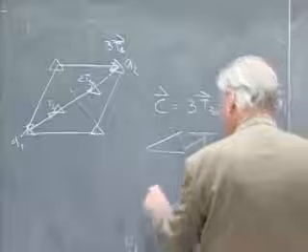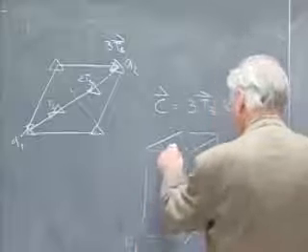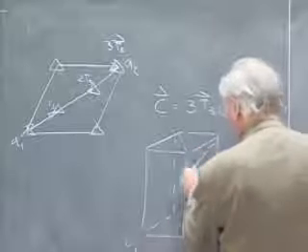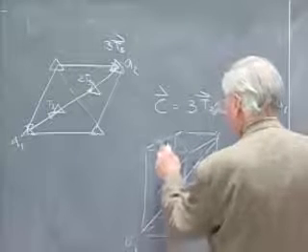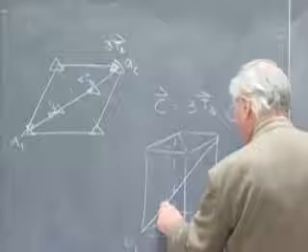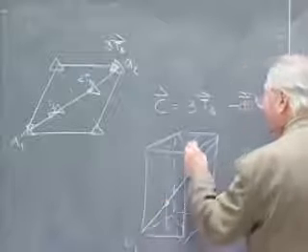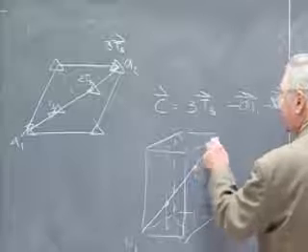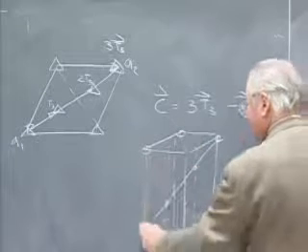It's going to be a peculiar sort of double body-centered cell. Because along the long diagonal of the hexagonal cell, I'll have one lattice point that's 1/3 of the way along that long diagonal, and another interior lattice point that's 2/3 of the way along that long diagonal.